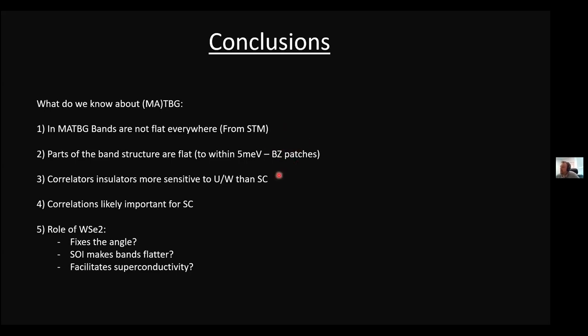These patches in the Brillouin zone might actually play a role. One thing you can say for sure from all these experiments is that correlated insulators are more sensitive to changes in this ratio than superconductivity. And at least from the experiments at the lowest angles, even at the lowest angle of 0.8 degrees, correlations do play a role. So at least we did not find superconductivity without any correlation physics. And these are mainly the things that we understand a little bit, but not fully.